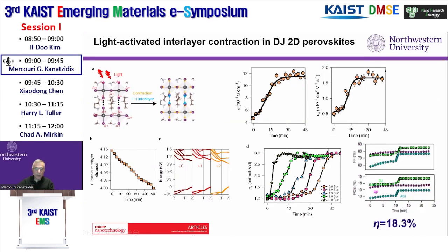We also noticed that the mobility and the charge transport in the stacking direction were becoming better. For example, here if you monitor conductivity versus time, you see after some time of illumination, conductivity becomes almost double. And as a result, the mobility also doubles. So what is going on here? And the way to explain this is, as these iodines are very close together, when we excite across the band gap, you create a hole, which is located in the iodine sublattice, especially the terminal one.